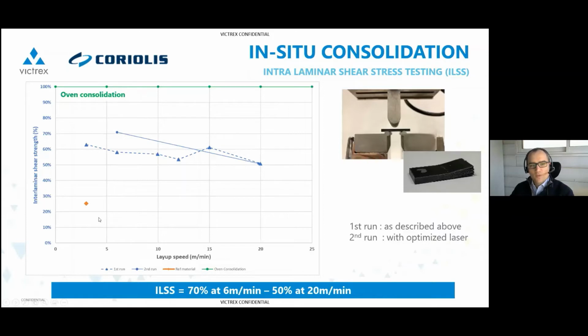And back to the reference material, we started with something like 25% at a low speed. So you can see that we are more or less 2.5 times stronger, if I can say it this way, with a speed of, let's say, 6 meters per minute, so 2 times faster. Again, that goes in the direction of saying we can achieve better or at least equal quality at much higher speed.